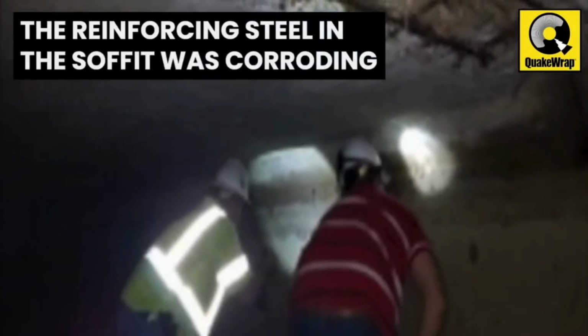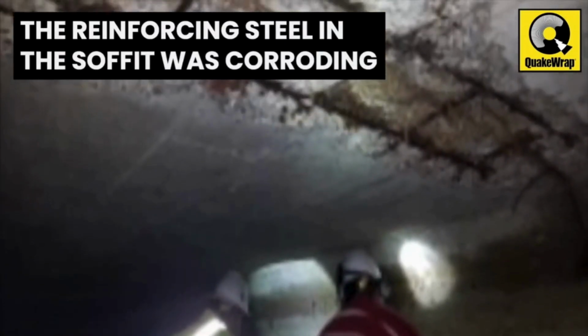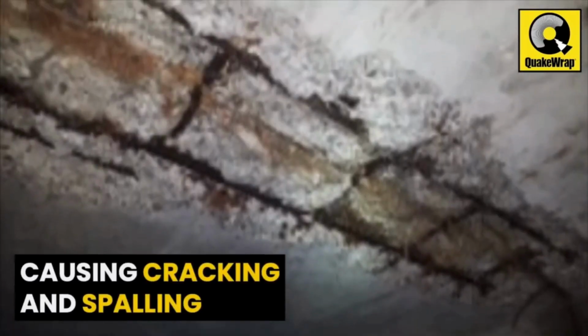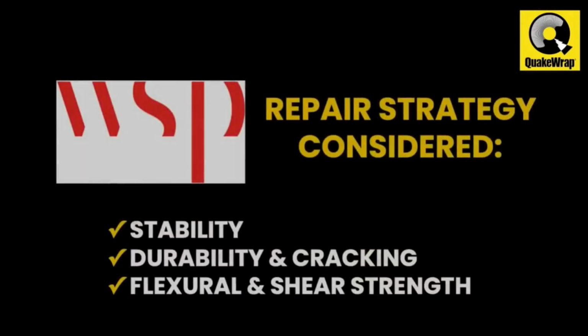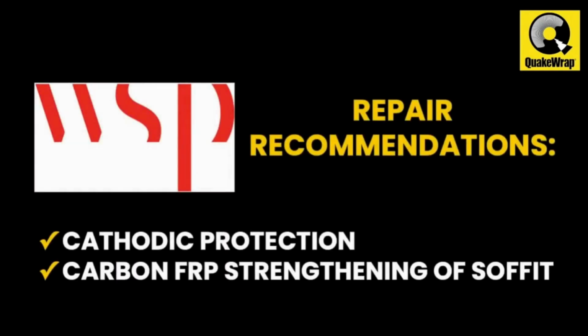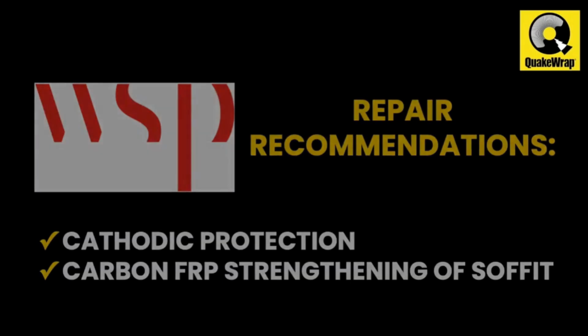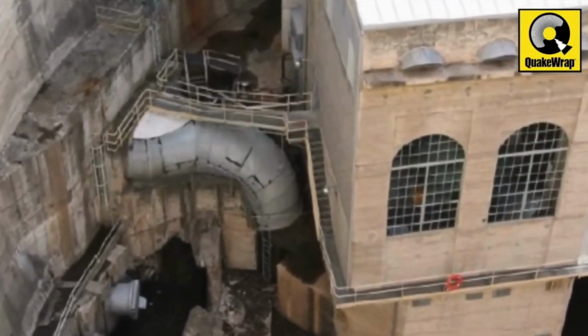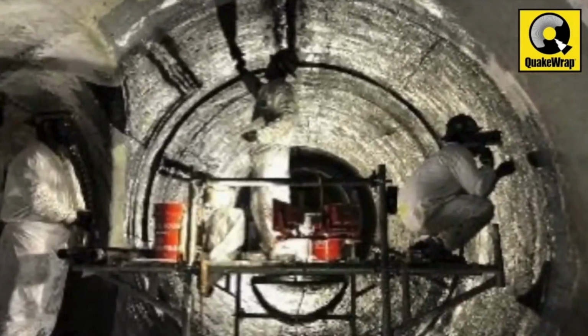An inspection in 2017 revealed that the reinforcing steel in the soffit of the culverts was corroding, causing cracking and spalling of the concrete. The consulting firm WSP was retained to evaluate the structure and recommend a repair strategy considering serviceability issues such as stability, durability, and cracking, plus strength of the culvert to carry the interstate freeway traffic load safely. WSP recommended a combination of repair of corroded regions with cathodic protection and the use of carbon FRP for strengthening of the soffits. Based on previously completed successful projects, such as the repair of a 90-year-old riveted penstock and